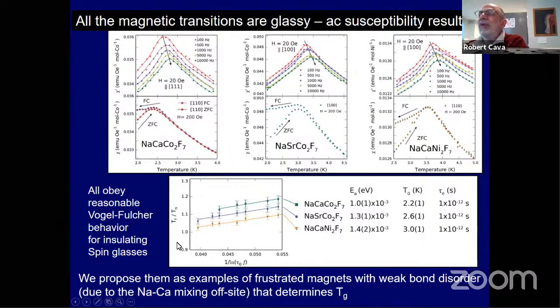And of course, you noticed already, I suppose, that to get the charge balance, we had to mix sodium and calcium or sodium and strontium on the non-magnetic rare earth site. Now that introduces disorder because sodium is +1 and calcium is +2, and you need to do that to balance the charge. But it introduces some kind of disorder on the lattice next to the magnetic lattice. And depending on how strongly that disorder interacts with the magnetic interactions on the cobalt sublattice, it'll give you either a negligible effect or something.